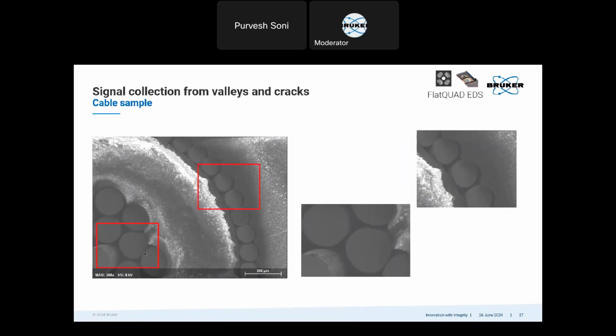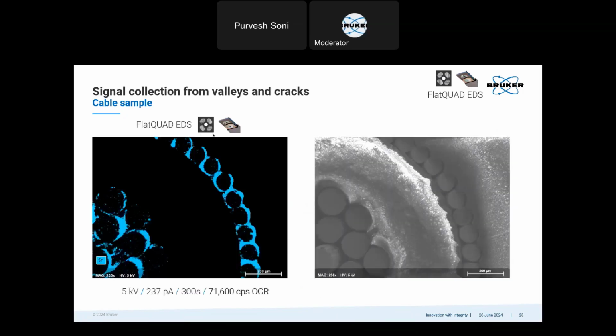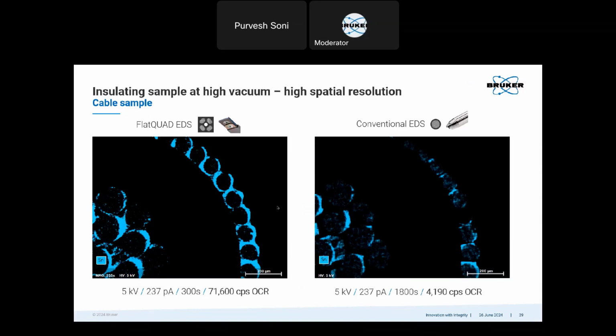And you see that there are some cracks and crevices and valleys in this material, so if you zoom into this, then you can see. With the FlatQuAD, because of the annular four-segment design, we could measure around this layer, and also in the valleys. And if we compare this with a conventional detector, then we can see that there's a strong data loss from around these copper wires where tin is coated.